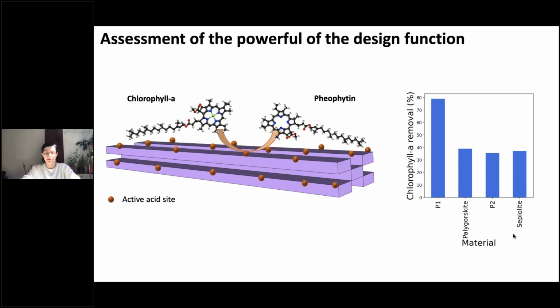we wanted to investigate the transferability of the optimal preparation between different clay materials. To address it, we explored another prototype based on sepiolite, but fixing the optimum disclosed for P1 for palygorskite. The catalytic activity of P2 indicates no improvement with respect to raw sepiolite or P1, indicating that the findings extracted by our approach are likely not transferable between different classes of materials, remarking the power of our design function in